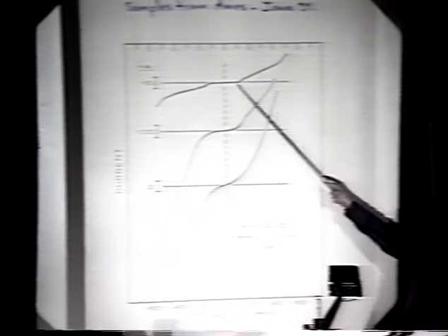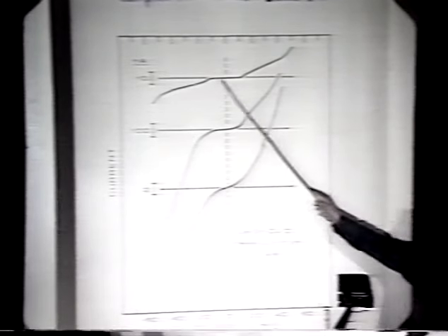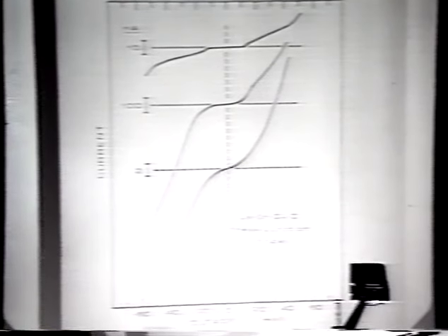Occasionally we'd see curves that had more structure, and here's the prize winner, a very nice convincing quasi-particle tunneling gap. And the distance from here to here is 28 millivolts. If you assume identical superconductors on either side, then that means the energy gap should be 7 millivolts, 1/4 of that. And the ratio of 2 delta over kB TC would be 4.5.